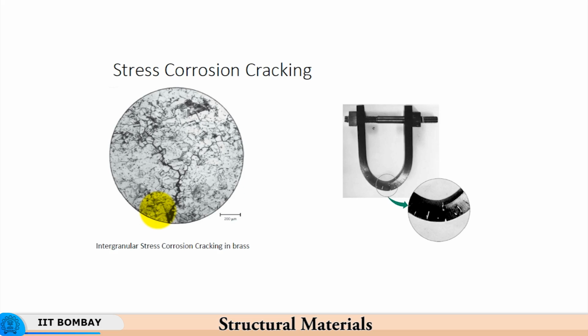So, for instance, if you have a certain degree of tensile stress applied to the material, as you see over here while bending, this was a bar which was bent in a U shape. The tensile region is at the surface, or tensile strain occurs at the surface, and this is where most of the dislocations and most of the stored energy of cold work are present. In the presence of a corrosive medium around it, the corrosive medium will readily find a means of entering or leaching away the metal, because whatever is at a higher stress level, higher strain level or higher dislocation density will behave anodic with respect to the rest of the material.